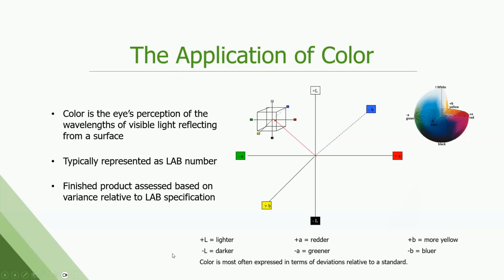Color, we talked about color. Very, very important, right? Consistency, how it looks to the eye, very important in the design world. So we do measure the LAB system, which is light, dark, yellow, blue, red, green, numerically for almost every color we run. We can't do it on the metallic micas, but we can do it on all the solid colors. Most lines are running to a spec that's plus or minus 0.5 deviation on this LAB scale from the controlled standard, which is incredibly tight. The overall calculation is called delta E of color change or color difference from a control to your sample. The human eye really doesn't start to pick up color change until you approach a delta E of 1, and we're controlling much lower than that from run to run.